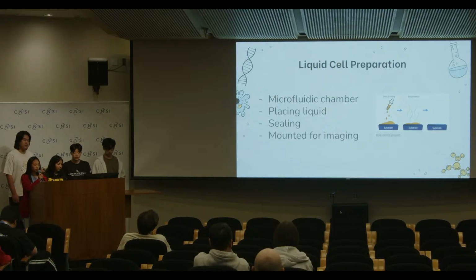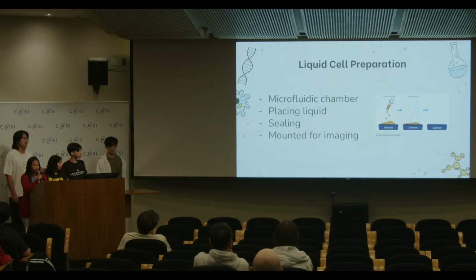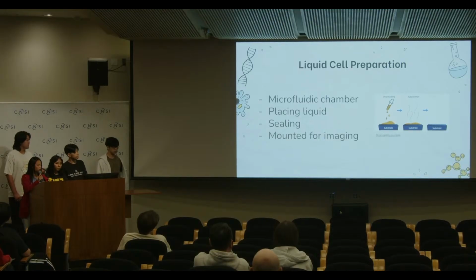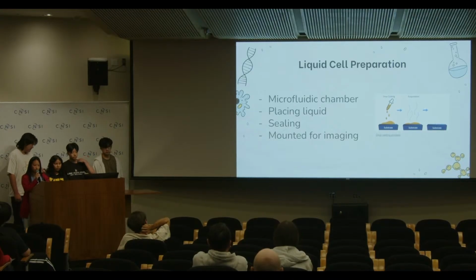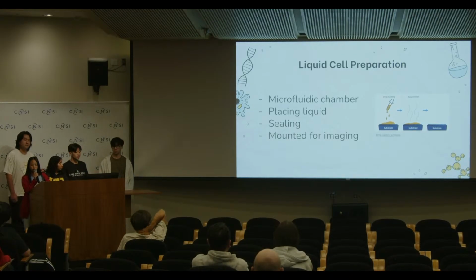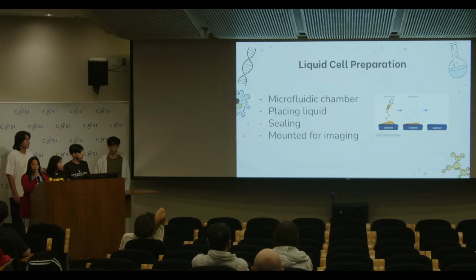So the liquid cell has two microchips with thin and electron-transparent membrane SiN windows, which create a microfluidic chamber to hold a liquid sample. A precise volume of liquid sample is placed onto the window of the bottom chip with an injector or by drop casting, which you can see in the image, ensuring a controlled environment with minimal evaporation and contamination, an even spread and no bubbles. The top and bottom chips are then aligned, squeezing the liquid sample.